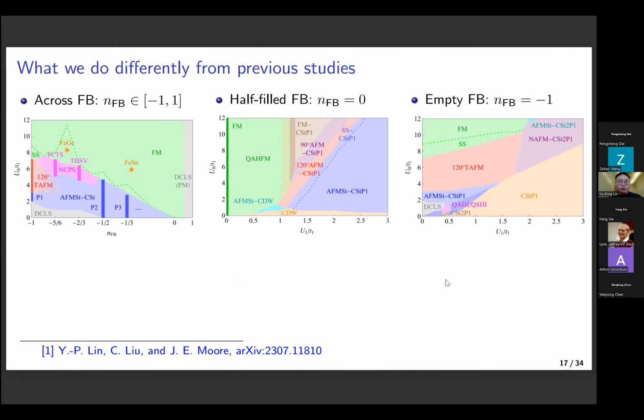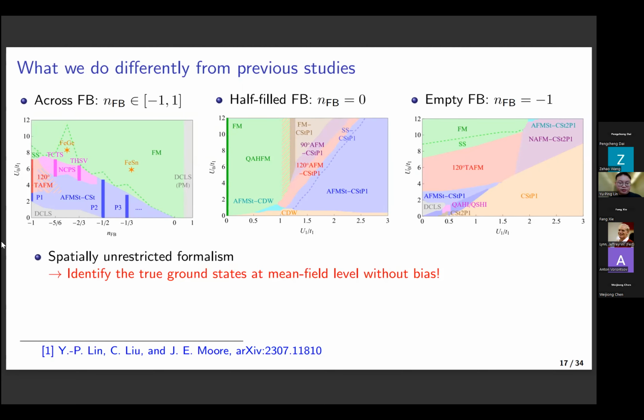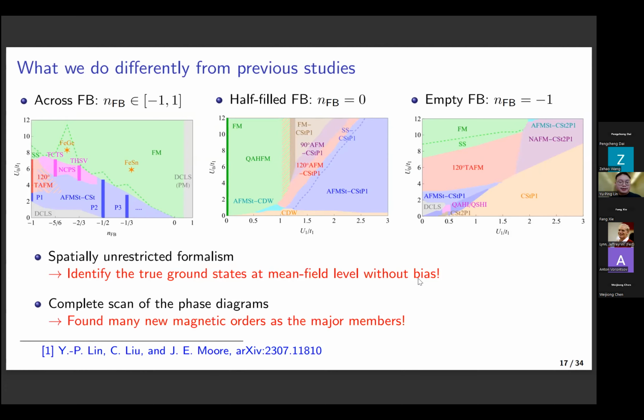So one question might be, what have we done differently from the previous studies? First, our Hartree-Fock analysis involved a spatially unrestricted formalism. That is, we do not put any ansatz or constraint on the wave function. And in this case, if we minimize the energy, we're able to really go to the true ground state, at least at the mean-field level, without any bias by an ansatz or constraint, like translation symmetry, for example. Secondly, we do a very complete scan of the phase diagram so that we can see many interesting phases that have never been found in the previous literature. That is, we're finding new magnetic orders as major members of the phase diagram.